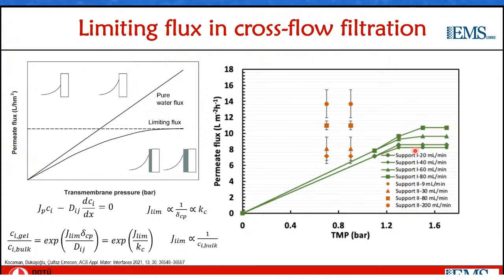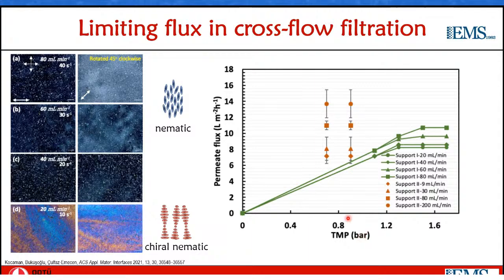So indeed, what we see is that as the cross-flow rate increases, so does the limiting flux. Same thing for the other support. And also what was quite nice to see, as expected, was that at the same cross-flow rate, so under the same hydrodynamic conditions, with the two different supports, we observe the same limiting flux. Only with the more permeable support, we observe it at a smaller transmembrane pressure. So then, how do these CNC layers on the support membranes look?